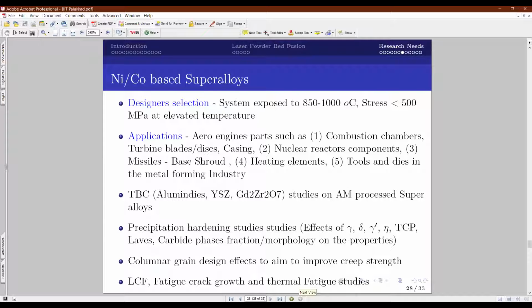And similarly, these alloys are strengthened, or their creep strength or fatigue strengths are improved, by the precipitation ordering treatment. So we form several ordered precipitates like gamma prime, and several undesirable phases like topologically close packed phases and Laves phases. And the morphology and the fraction of carbide phases or boride phases are very important. In the conventional process, the way in which you get them is definitely different in the 3D printed one. So understanding the precipitation ordering treatment on 3D printed components is of paramount importance. So I urge people to focus on the heat treatment studies on these superalloys. And there are some reports which state that columnar grain design is possible through 3D printing, which if we achieve in India, definitely it will be a great achievement because it will help to improve the creep strength.